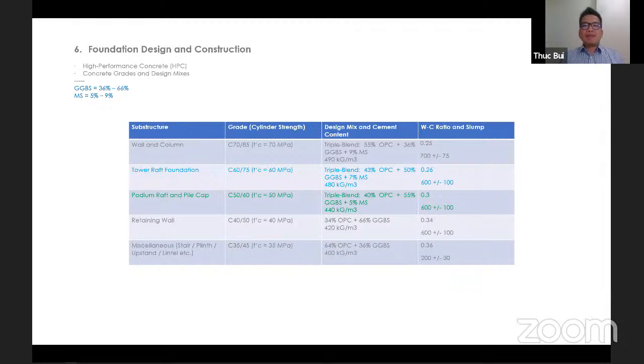We've been designing the foundation using high performance concrete. The concrete cylinder strength for the tower raft and podium raft is 60 MPa and 50 MPa. We use triple blend concrete. Triple blend concrete mixes with 50 to 55% GGBS and 5 to 7% microsilica.